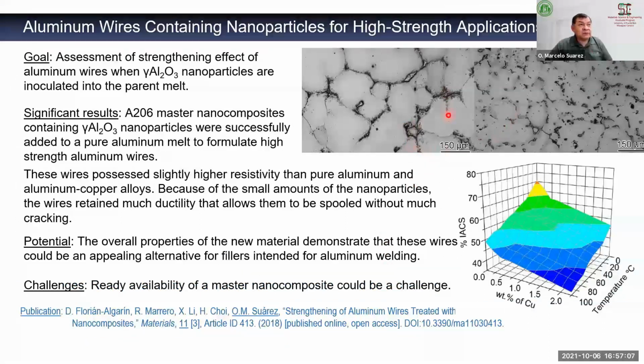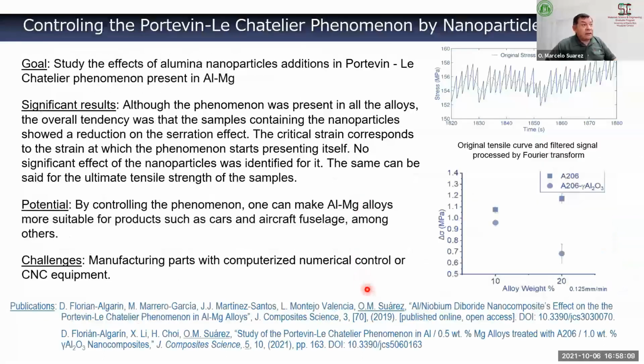Through a collaboration with a professor in UCLA, we were working with these nanocomposites containing gamma alumina nanoparticles, and another grad student started working in producing wires made of these nanocomposites. Final idea was to see if we could have these wires as sort of fillers for TIG welding of aluminum. That's why we were measuring conductivity of the wire, because if it has high resistivity, then with the arc of the TIG tip, we could increase the temperature of the filler, so it would melt really fast.